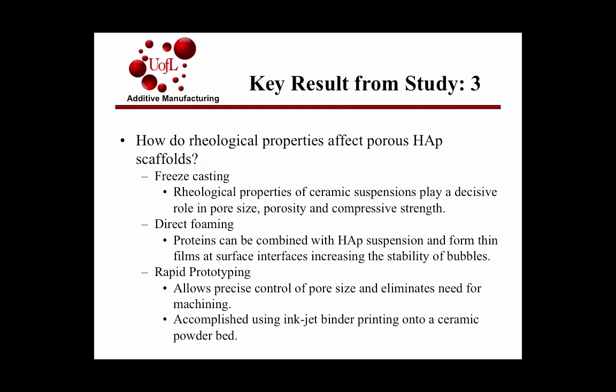All right, and then we're looking at the rheological properties' effect on porous scaffolds. And there are 4 different methods, well, 3 that I'm examining here, of accomplishing this. Freeze casting, where they did determine, and this is a really generic explanation, that the rheological properties played a decisive role in the pore size, porosity, and compressive strength, which, as we've addressed, for a bone substitute material, you need to have high mechanical strength in the compressive direction, and you also need to have a porous material that's going to incite new bone growth.